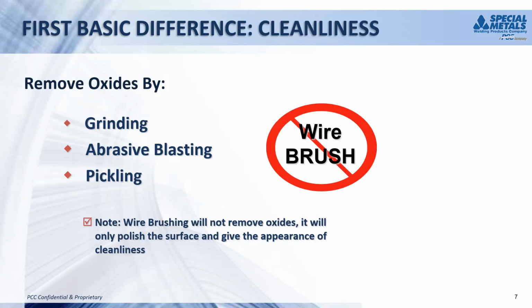So we can remove the oxides by grinding, abrasive blasting, and pickling. And we've got wire brush. We've got to, do not use wire brush. That's not exactly right. Wire brushing will not remove the heavy, tenacious oxides that attach themselves to nickel alloys, like in high temperature service or in hot rolling. Wire brushing between passes with all processes is a good thing to do to keep it clean. But if you have a heavy, tightly adherent oxide, wire brushing won't remove it. What it does is it shines it up and makes it look like it's clean, but it's still there.